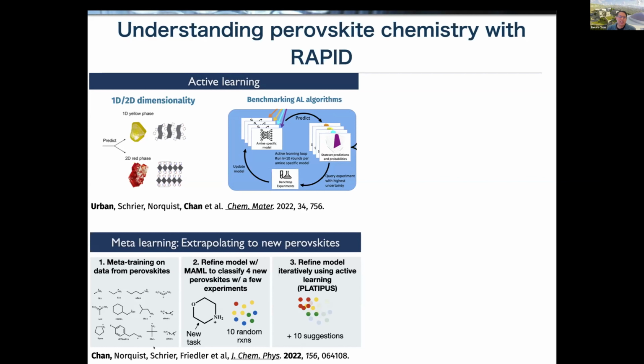But when we tried to use our very large data set, so we trained on a data set of over 17,000 perovskite reactions on 50 different perovskites. But when we tried to predict the reaction conditions for a 51st perovskite, it was terrible, because machine learning models are typically not really good at extrapolating to parameter spaces that they haven't explored.